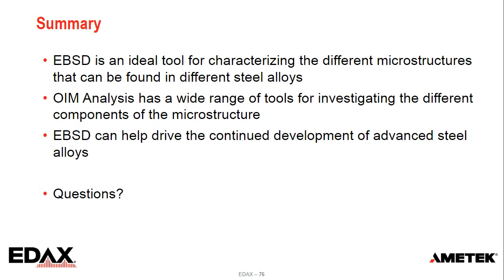Now, we're always a little careful of saying, is an image quality value a definitive number? Can you compare one sample at an image quality of 100 to another sample at an image quality of 100? Generally, we say be very careful of that because there's a lot of factors that can affect image quality. We published a paper about this about 15 years ago, because it can depend on your beam current, your camera settings, and your sample preparation. So oftentimes we look at image quality relative to within a map. People have done some work trying to standardize and normalize that, and I've seen stuff to say, yeah, I believe it, but you're looking at a subset. I've also had cases where I vent the chamber and repolish a sample, or rescan it without doing anything else, and my image quality can vary just from that cycle. So you have to control your variables pretty carefully.